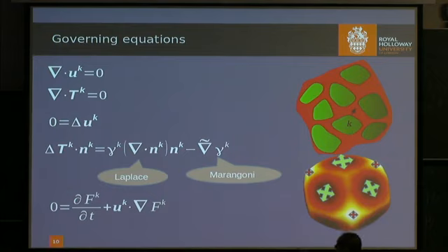Basically, the Marangoni term arises from the fact that you might actually have variation in the surface tension along the surface of a grain. Uli showed us these beautiful images where it was pretty obvious that in the grains you do have varying surface tension. So I'm showing an image here just to give you an idea. If we had a grain, in this specific case an isotropic grain, you have a different surface tension at the grain-grain contact, a different surface tension at the grain-melt contact, and this Marangoni term captures that variation along the surface.